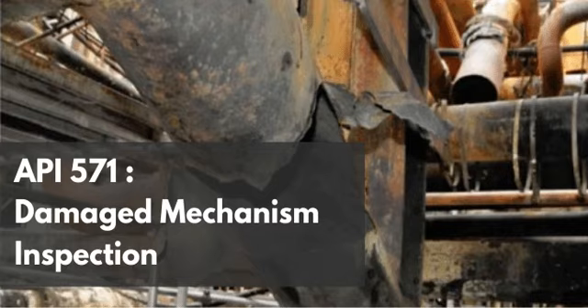engineers must actively avoid specifying the higher chromium ferritic stainless steels. So you have to keep the 430 and the 446 completely out of that temperature band. Yes. You also have to absolutely avoid the Duplex steels in that range. But what if the process fluid requires some level of chromium for corrosion resistance? I mean, what if plain carbon steel isn't enough?